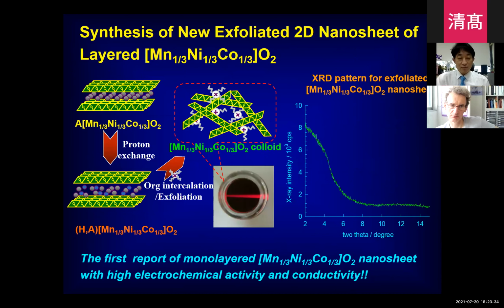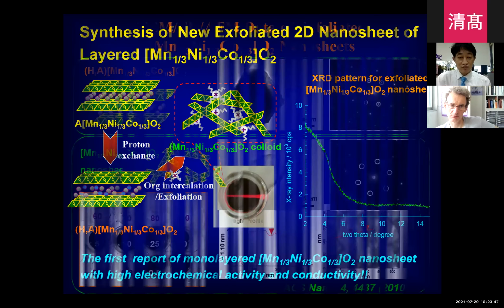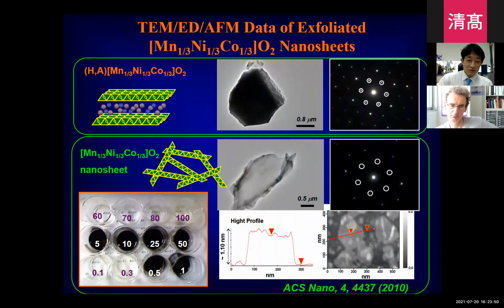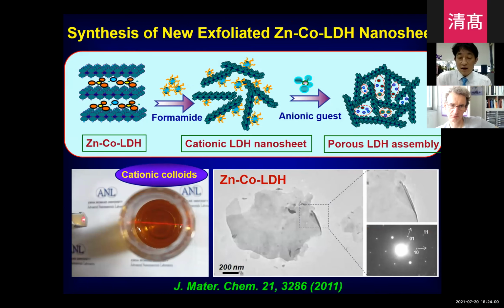One of the examples is a very famous material for the cathode of lithium-ion batteries. We synthesized monolayered manganese nickel cobalt oxide by the intercalation-based exfoliation process. We can confirm the formation of monolayered nanosheets from the TEM and AFM analysis. One thing I want to emphasize is that most of the inorganic nanosheets have surface charge, and most of them are negatively charged. One valuable exception is the LDH, because the LDH has a positive surface charge. So by exfoliating this material, we can get a cationic inorganic nanosheet, as you can see here.